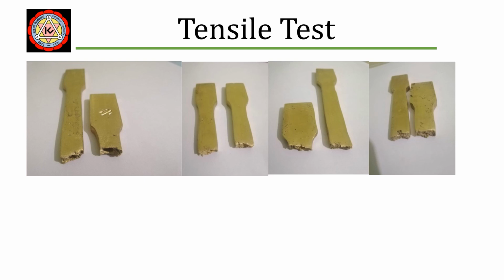Similarly, in specimen 3, fracture occurred near the grip section instead of the gauge section. This might also be due to casting defects and improper gripping of the specimens during testing.